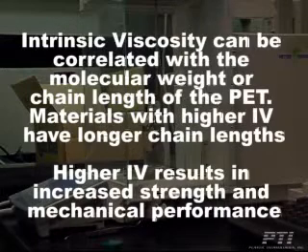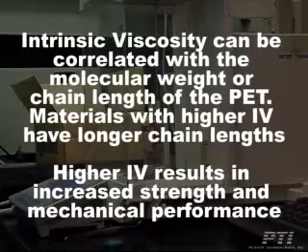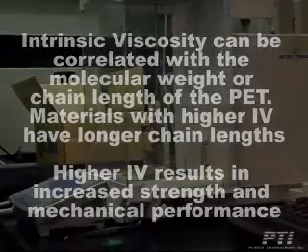Intrinsic viscosity can be correlated with the molecular weight or chain length of the PET. Materials with higher IV have longer chain lengths, which results in increased strength and mechanical performance.